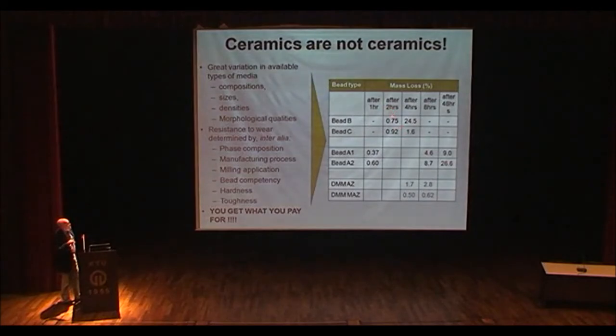After 2 hours of milling in a test mill, they look fantastic, very similar. After 4 hours, when that nice shiny coat's gone, voila, this guy's collapsed, he's lost 24% of the mass, this one's still good. That's the competency, the shell effect that you have to watch out for. Again here, we find that in a 1 hour test right through, an 8 hour test even, things look good. Right up here, with a slight difference, but suddenly, again, there's a massive difference after 48 hours. That shell has gone and worn down. So this is what you have to look for. You need that competency and the toughness.